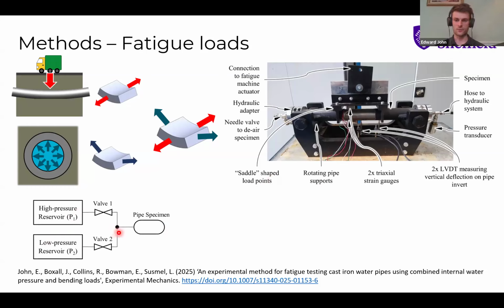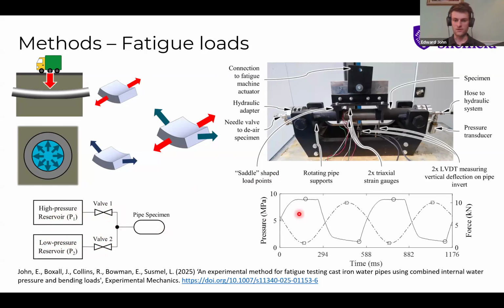And this pipe could also be pressurized cyclically by the system shown in this schematic here, where we have a high pressure reservoir and a low pressure reservoir. By opening and closing the valves, you can cycle the pressure in the pipe. And this plot shows the load profiles that we use. The amplitude was constant, so the bending or pressure load just cycled until the pipe failed.